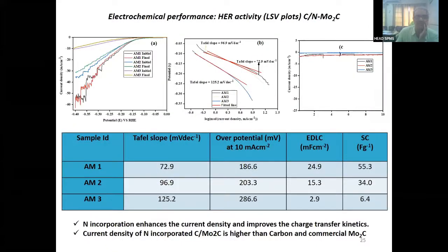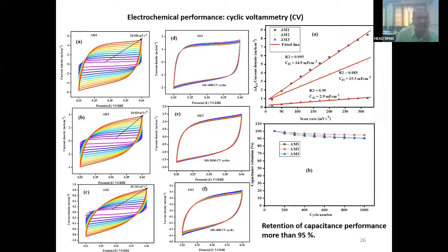Okay. We have measured the electrochemical properties here. You will find that this is a very good class of material. You can see that we have taken the potential versus current curve at different cycles. What I would like to say is that we could get retention of the capacitance performance of more than 95% over several cycles, not one cycle, several hundred cycles, from this material.